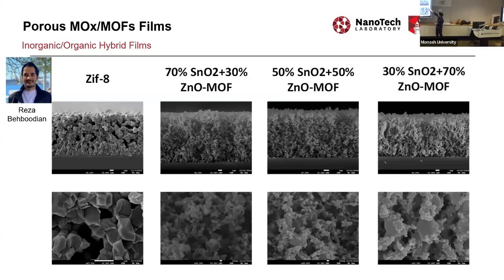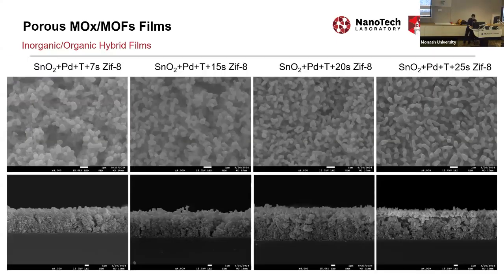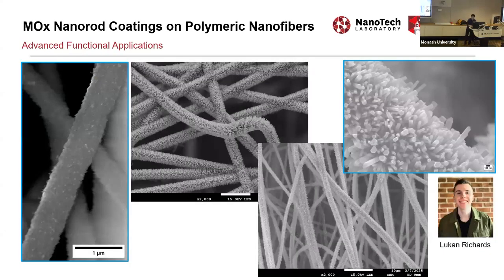Again, this is from the side view. It's extremely porous. The base is tin oxide, but in the middle you can see that, as a composite, it has all these ZIF8 embedded into the system. You can also do it with a bottom layer of tin oxide. The top layer was zinc oxide exposed to ligand. The bottom layer didn't change at all, but the top layer is converted to ZIF8.